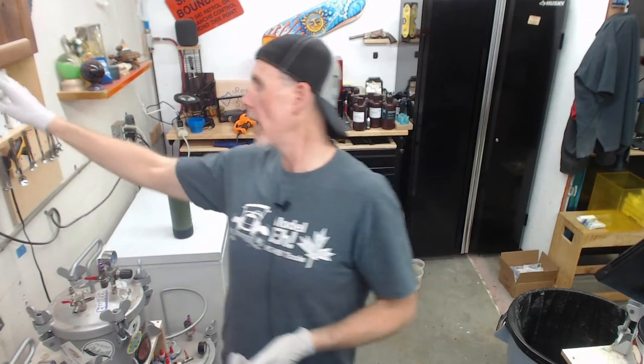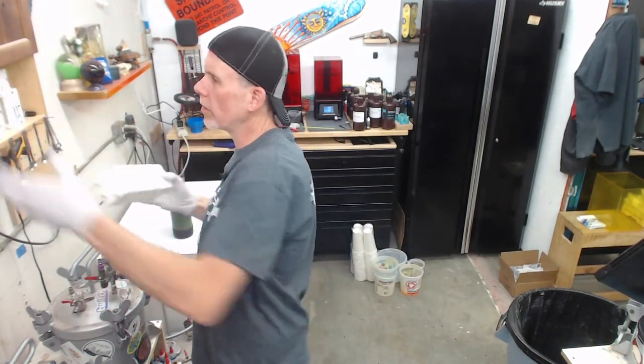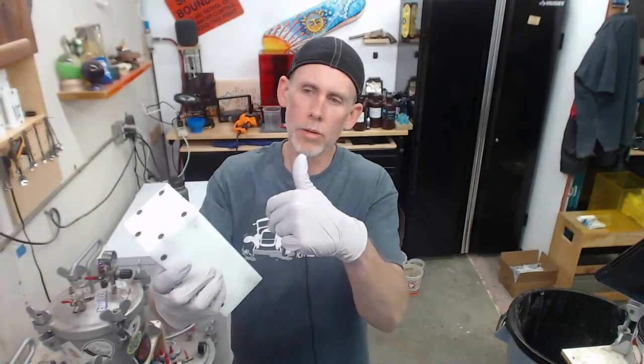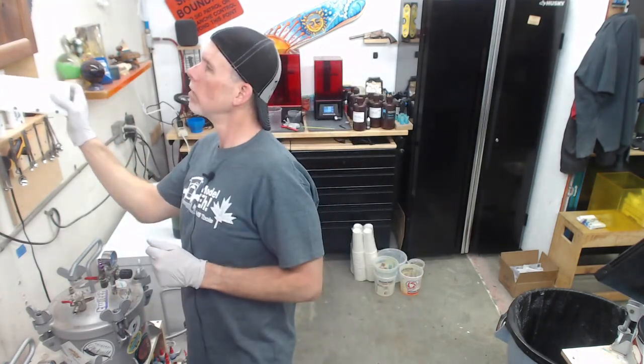Yeah, you can't cast a gigantic blank with that stuff. It's a normal epoxy. I've made 2-inch. I would agree. You can make a brick that's like 3/4 or 1 inch thick, and that's totally fine. 2-inch handle blanks like this, 2 inches by about 6.5, it gets warm at that point.